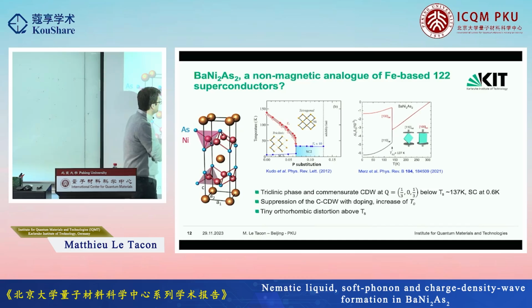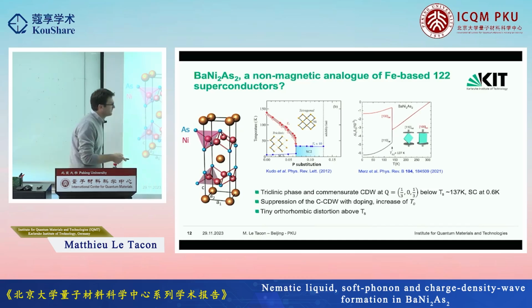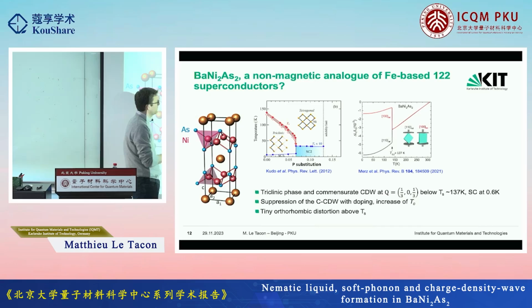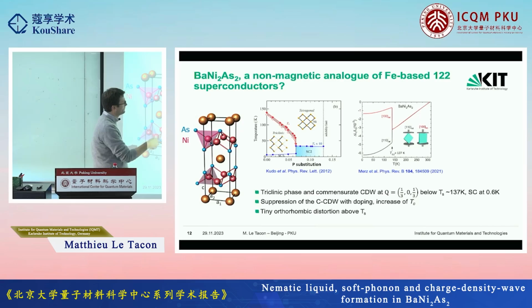My colleagues Christoph Meingast and Michael Merz looked into these materials, which have this large triclinic transition, and they did the dilatometry measurements. What they found is that when you cool the material down, you do see this very strong first order transition. This corresponds to this transition here. Actually, it also has a hysteresis if you warm up. So here it is upon cooling at 137 K, and you nicely see this big first order transition.